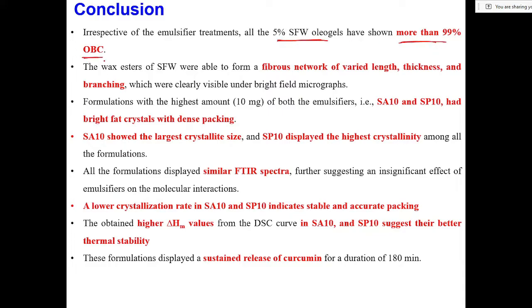Okay, so in conclusion we found that the oleogels we have developed had more than 99% OBC, that means the oil binding capacity. Then all the samples had a fibrous network. However, there was a variation in the length, thickness and branching depending upon the composition of the oleogel. Then SA10 and SP10 had bright fat crystals with dense packing. That means when we increase solid emulsifiers in the system, there is an increase in the packing density of the fats. SA10 showed the largest crystallite size, whereas SP10 displayed the highest crystallinity.